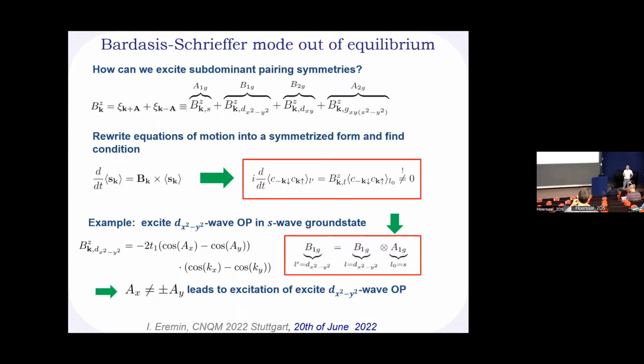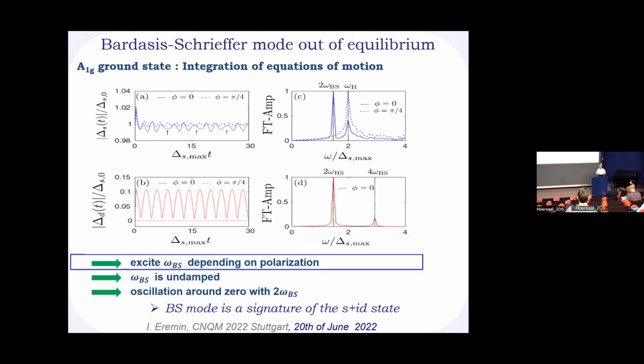Necessarily, of course, you do excite a Bardasis-Schrieffer mode, because what is happening in this case is that your pseudomagnetic field can be decomposed into the irreducible representations. And basically, what you just need to excite a subleading dx² minus y² order parameter in the S-wave ground state is just to introduce an asymmetry in the vector potential, introduce the correct polarization of the light. So which you can immediately visualize. So in this case, if you would just look at the Higgs oscillation, you start to see that there is an additional mode, and this additional mode is basically your Bardasis-Schrieffer mode. Now, the important thing is that first it is undamped, so its intensity is much higher than the Higgs mode, because the Higgs mode coincides with a continuum.